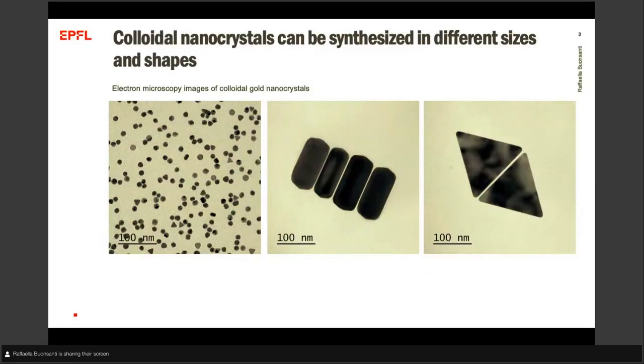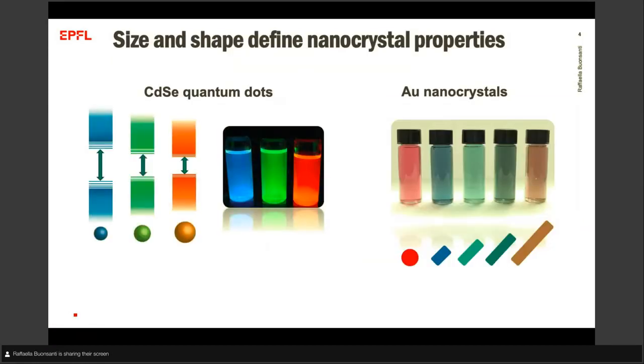Here I'm showing some electron microscopy images of gold nanoparticles. So we can make them in different sizes and shapes. And why is it important to control size and shape? It is because the properties of nanocrystals are defined by size and shape. So regarding optical properties, here already Leah showed beautiful fluorescent vials. So these are cadmium selenide quantum dots, where when we change the size, because of quantum confinement effect, we change the band gap and therefore the emission properties.